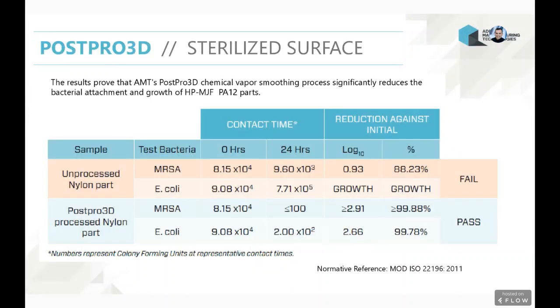PostPro3D comes in, and by erasing all the crack initiation sites and all the surface porosity, makes a product more durable. It increases the elongation at break and the fatigue resistance of the product, whether it is a rigid or an elastomeric polymer. And as this graph presents, we've done the testing, and this analysis has shown that smooth parts have passed the antimicrobial test, showing a significant reduction of bacterial growth, quantified as above 99.5% against the growth of MRSA or E. coli, while the as-printed parts have failed the test, showing a limited reduction for MRSA and significant growth actually for E. coli over time.